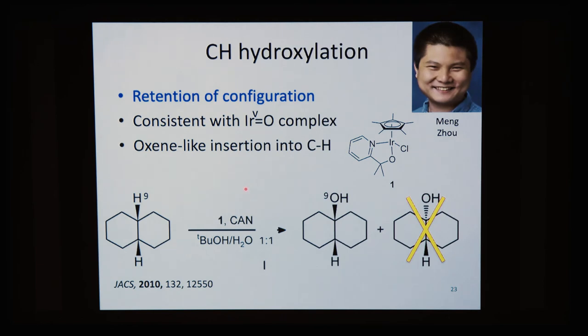Now, the oxo intermediate that Odile hypothesized is also consistent with the retention of configuration that occurs when CH hydroxylation occurs. In the case of cis-decalin, oxidation by standard metal oxo units, such as P450 in biology, gives the trans carbinol on the right, which does not occur with the iridium oxo intermediate, and which gives the cis. And that is because, presumably, the standard oxo pulls a hydrogen off the 9 position and produces a radical which rapidly inverts, whereas the oxene-like insertion into the CH bond that Odile hypothesizes is consistent with retention of the configuration.